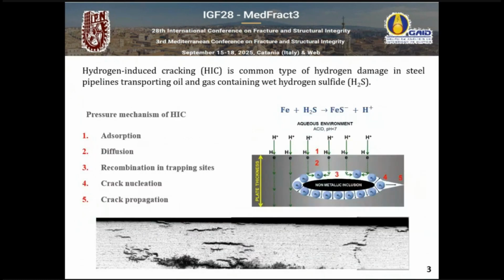Well, the most widely accepted theory of HIC is the so-called pressure mechanism, where the corrosion reaction of the iron releases hydrogen, but then the sulfur prevents the hydrogen from combining to form hydrogen gas. So the hydrogen is absorbed in the so-called atomic state. We don't know what the real state of this hydrogen is, so we are just okay with calling it atomic hydrogen.